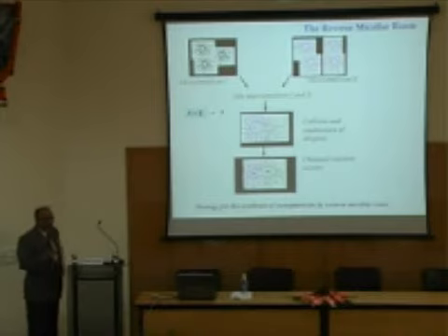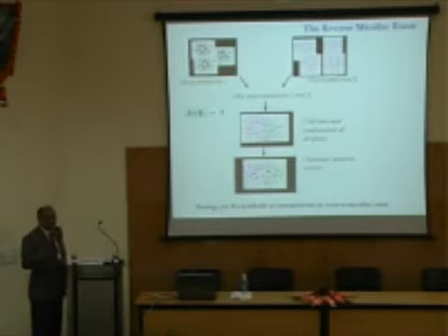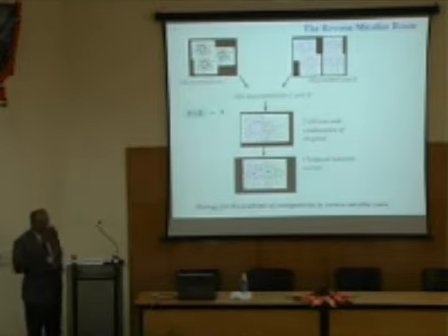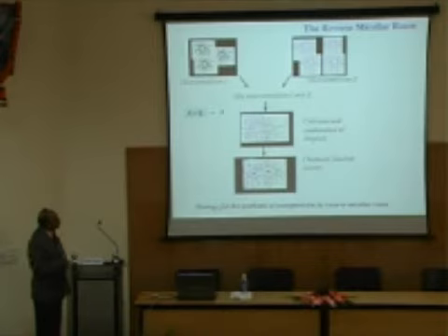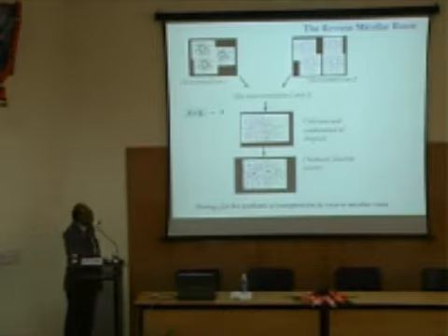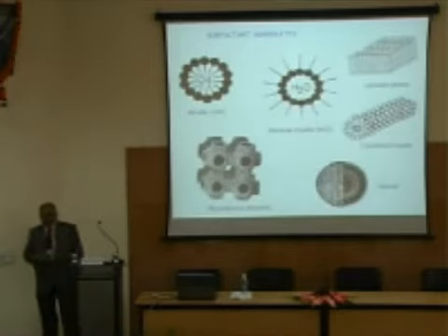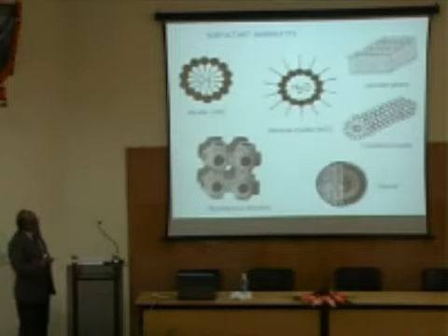So, normally if you do not use microemulsions, you can also do this reaction, but you will get large size particles. So, you will get micron size. Normal particles you will get are micron size. But if you use microemulsions, you will get the same particles, but restrained to the size of the structure which you have created in solution. And so, you will get small sized objects, and this is a way of control of the size of these particles. Okay?